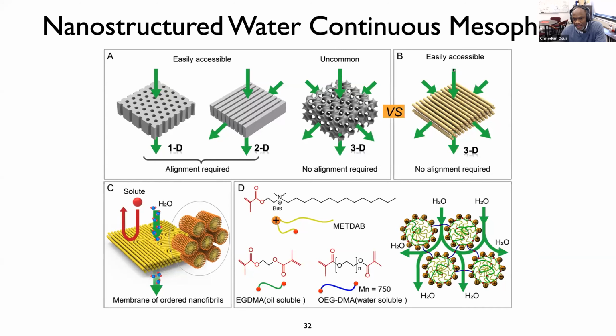What we've been looking at is selective transport by flow around cylindrical objects that have been polymerized in a water continuous medium. Okay, so there was a bit of serendipity involved in the discovery of these materials. These are interesting materials because this mesophase, the so-called direct hexagonal lyotropic mesophase, is readily accessible over a broad variety of molecular species. Selective transport around these cylindrical objects requires no alignment of the material, and so the processing implications are attractive. You don't need to have a separate process step for the alignment of the transport regulating features. And the idea is that then the transport regulating features are formed by the separation between the exterior surfaces of nearest neighbor cylinders.